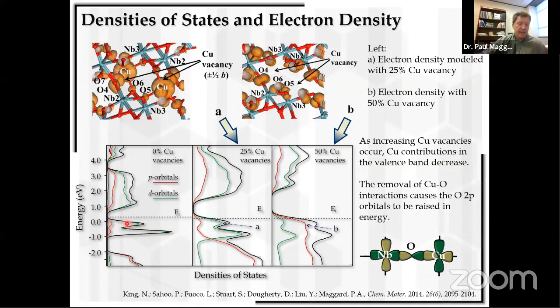Okay? And here we have the valence band, and here the conduction band. And at the valence band edge, what you see emerging in the red peak here, and then here, and here, are the oxygen p orbitals. These p orbitals are getting higher and higher in energy as copper is removed. That's because as copper is removed in the structure, as shown